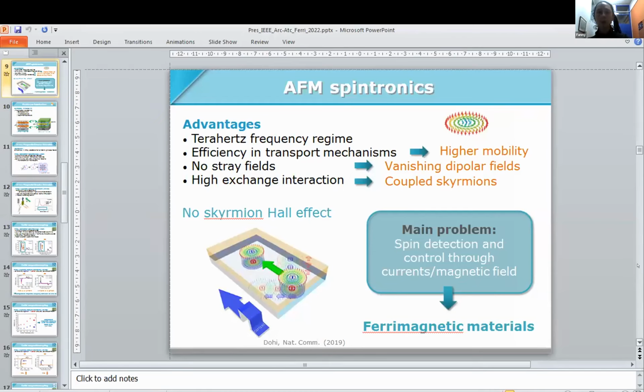But the main problem in using antiferromagnetic materials is when we want to deal with the spin detection and control, either by current or magnetic field. And so one possible solution is to deal with ferrimagnetic materials, which on one hand will continue to have the advantages of antiferromagnetic spintronics, especially the higher mobility and the coupling between skyrmions. But since you have a ferrimagnet, you still have a magnetic moment that you will be able to control and to detect.